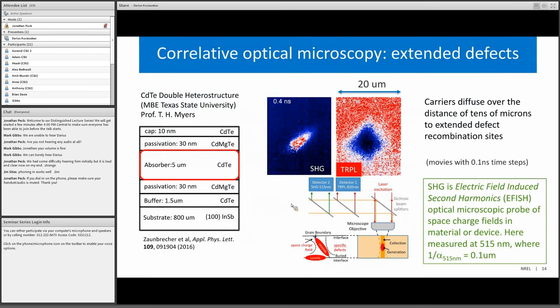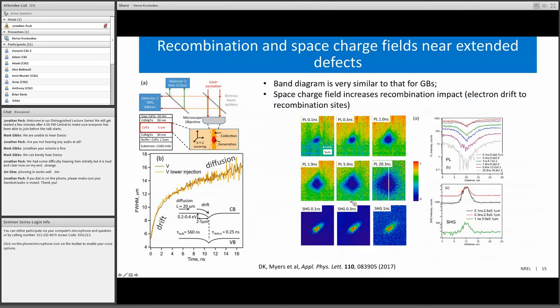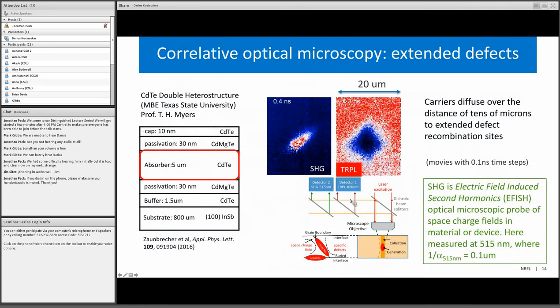So to illustrate the microscopy, the easiest is to start with a very simple crystalline sample that has only one type of defect, which in this case are stacking faults. The samples are grown not too far from Austin in the lab of Professor Myers. And if I am able to start this movie, you will see how luminescence is changing over time. So the time step in this movie is 0.1 nanoseconds, and you see that the size of this dark area is growing in time.